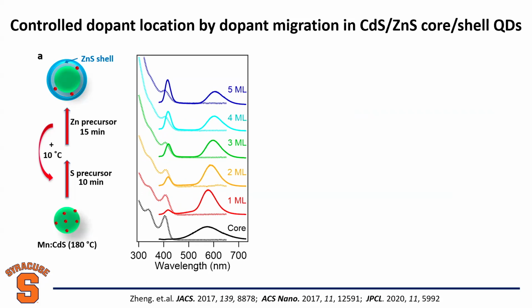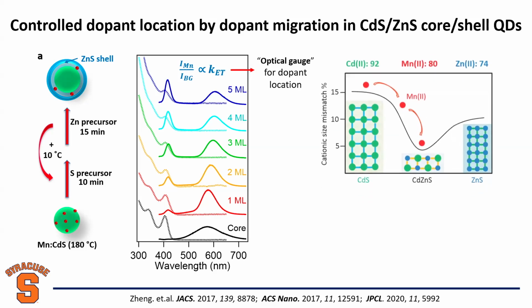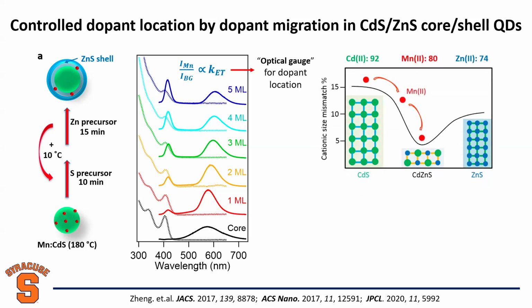People had never seen this before. What happened here? Now we know that manganese emission comes from host-to-dopant energy transfer. We thought we might have somehow separated the host and dopant, right? For example, if we're in the same room, very close, we can communicate. Outside the building, further away, no energy transfer, no communication. So same thing here. So we think manganese migrates away from the core. And it's really hard to study, right? Because you're talking about a few atoms. And we found the ratio between manganese emission and host emission can act as an optical gauge for dopant location. This is a new tool we developed. This is what we think would happen, right? If you put dopant manganese in sulfide dots, you're going to replace the metal site, because manganese is a metal.